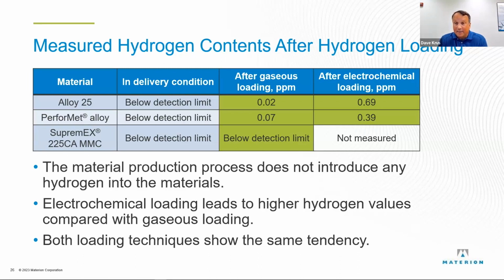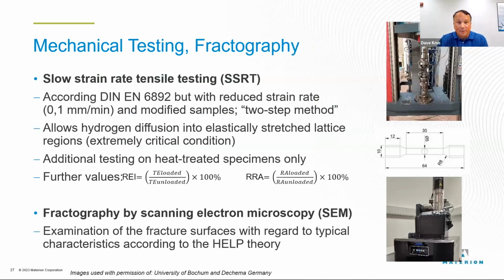We have not yet used the Supremex in the electrochemical loading in the liquid bath, but as you'd expect, it's slightly higher, but still below 1 part per million. So it's not much hydrogen getting into these samples.